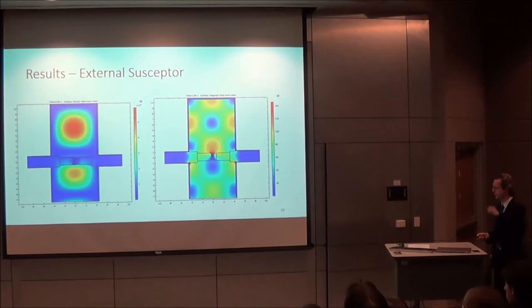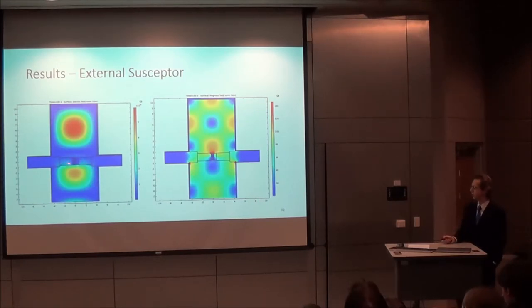And here are the numerical results. I'm showing the electric field and magnetic field distributions. You can still see that the joint itself and the pressure fixture are reflecting the bulk of the energy in the electric field. However, there's high enough intensity of magnetic field energy within the susceptor itself to actually heat and then transfer that heat to the joint.